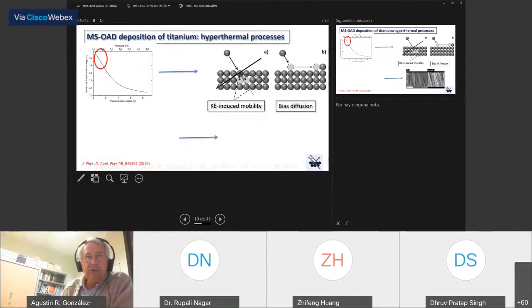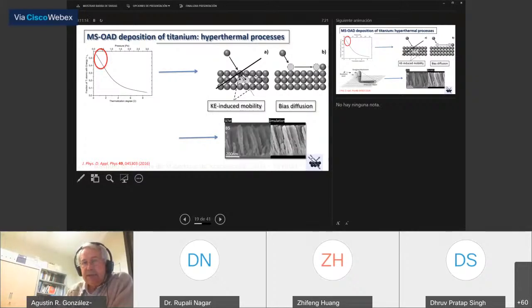Well, I cannot go into details, but the question is that in this and in many other situations where we have particles which have a certain energy above a certain energetic threshold on the surface, arriving particles may induce mobility of the atoms, either from what we call kinetic induced mobility of the atoms or some biased diffusion. And modeling this effect in the magnetron sputtering situation, we can reproduce this nanostructure perfectly well.